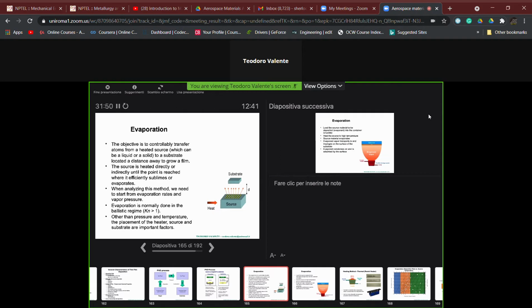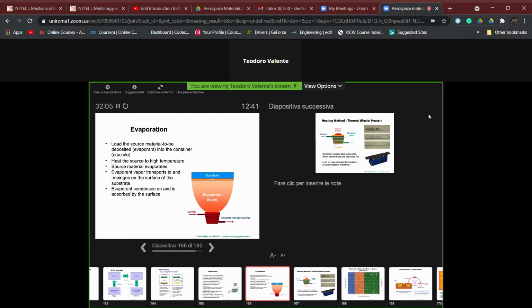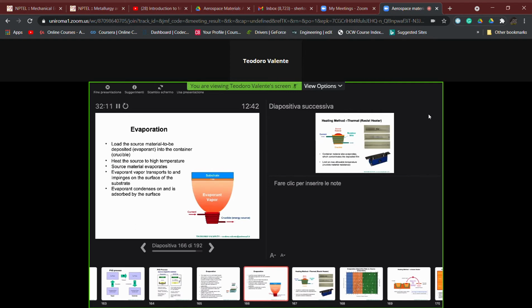Let me say, in this case, again, the most simple configuration is that we get evaporation by heating our target, that is, by heating our source. And how can it be done? For example, the source material, that is the target, can be put inside a crucible. And this crucible can be heated by letting a current flow around the crucible itself. And so by Joule effect, we have heating of the solid phase, which is inside the crucible,